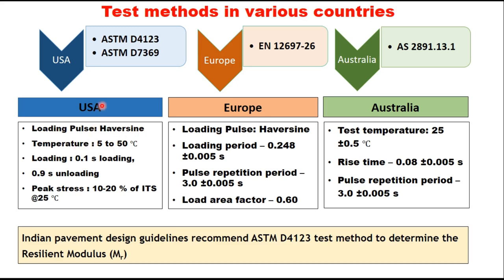The testing temperature in ASTM is suggested as 5 to 50 degrees centigrade. Resilient modulus is very sensitive to testing temperature. The loading time is 0.1 second and unloading time is 0.9 second. The peak stress in the ASTM method is 10 to 20% of indirect tensile strength of the material at 25 degrees centigrade.